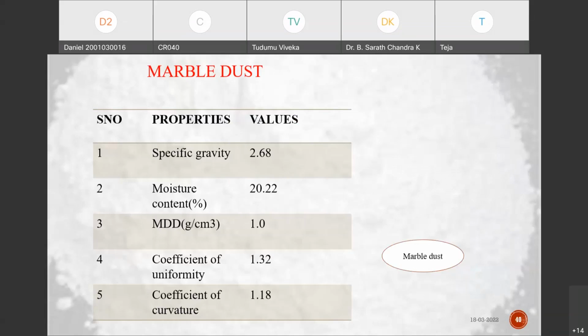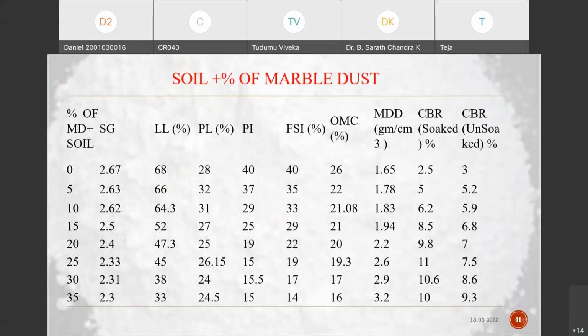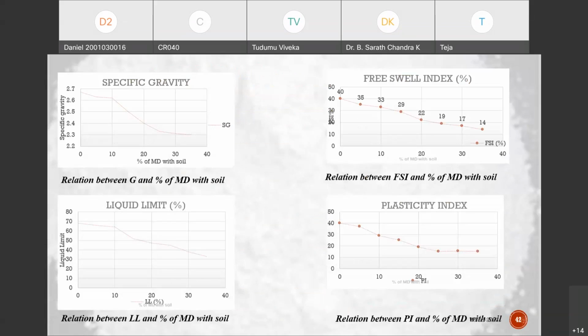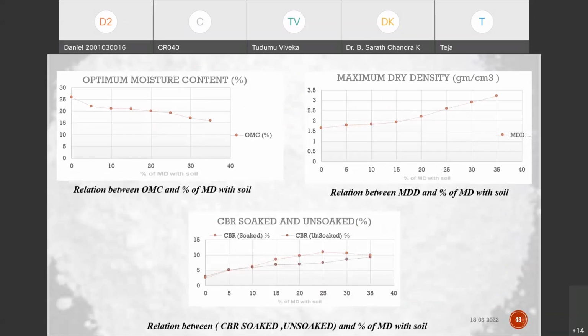So these are the properties of the marble dust. If you see the marble dust, these are the obtained results, liquid limit, plastic limit, and the different properties with the 0, 5, 10, 15, 20, 25, 30, 35 percentages of marble dust. If you see the results here, the specific gravity, free swell, plastic, and liquid limit are decreasing with respect to the increase in the percentage of the marble dust. And the optimum moisture content also decreases with respect to the increase in the percentage of the marble dust.